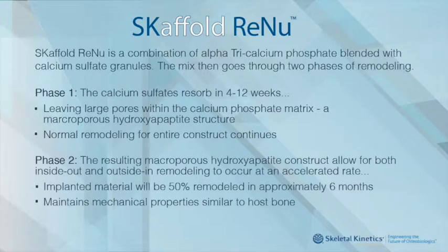In phase 2, this resulting macroporous hydroxyapatite, which is now a bone graft, allows for outside-in and also inside-out graft remodeling. The implanted material should be around 50% remodeled in about 6 months, and typically takes around 1 to 2 years to completely remodel into new bone. On the screen now are images that illustrate this process.